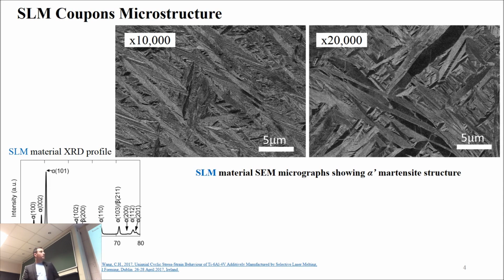Before we start doing any cyclic tests, of course, we did some monotonic tests. We couldn't rely on the tests which have been done in the past by other researchers, either within the university or other universities. So we tested the wrought metal, which was the typical mill annealed wrought metal we obtained from the market, and the SLM produced metals. What we have seen is that both exhibit very similar behavior in terms of the ratio of the ultimate stress to the yield stress.